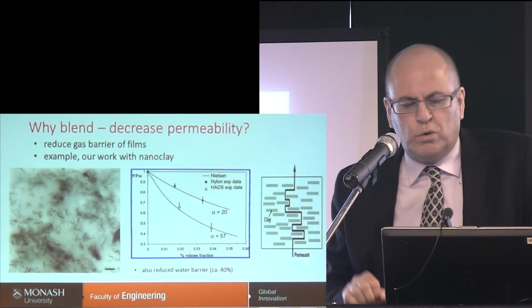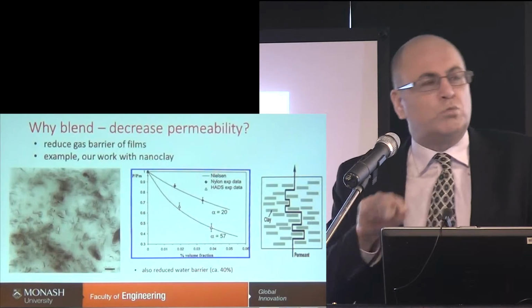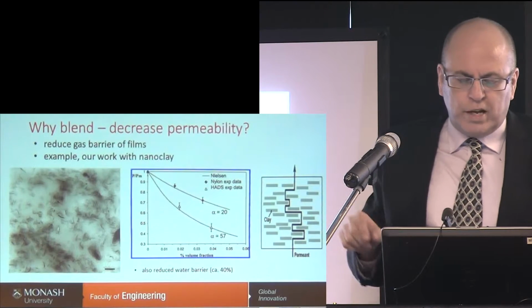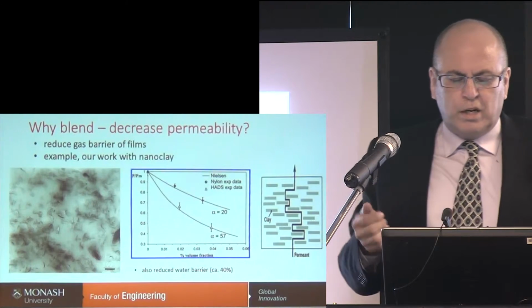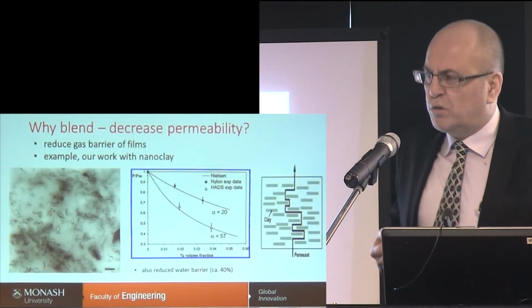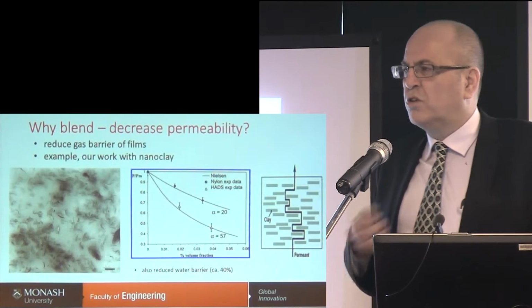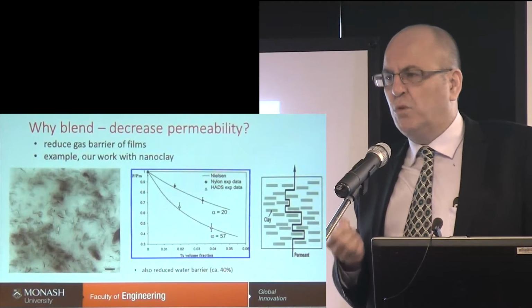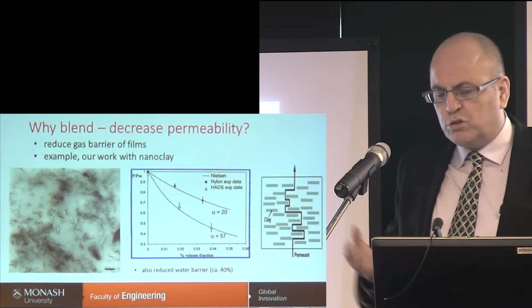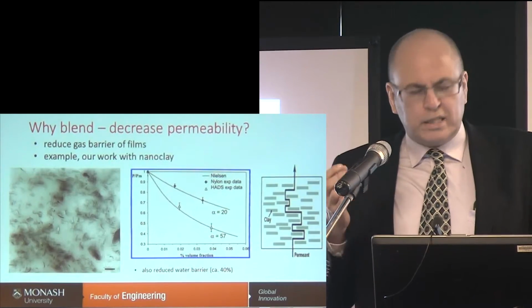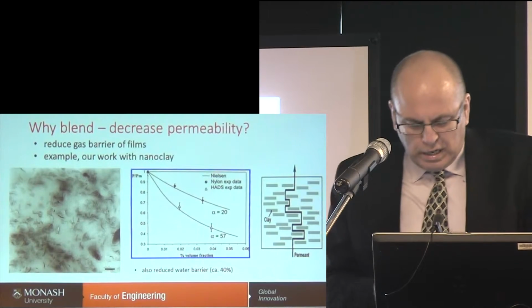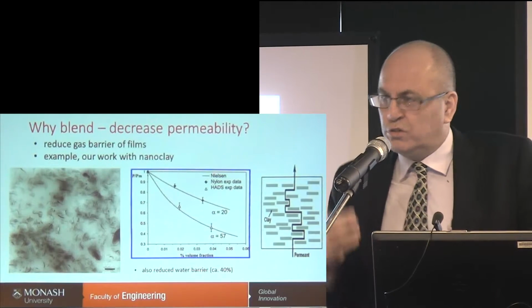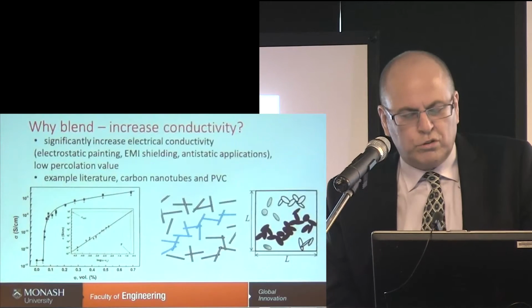What's another reason why you blend with nanoparticles? This is what we did with nanoclay. What we found is that by putting in a couple of percent of nanoclay, we could decrease the permeability, such as to oxygen or other gases, by about half or more. That's by the tortuous path on the far right for the gas to get through. So the nano, in this case, sheet-like nanomaterials, nanoclays, are able to introduce that.